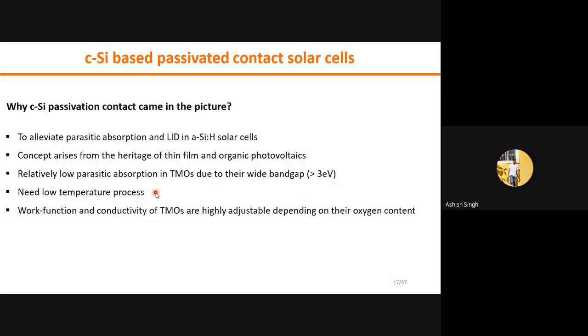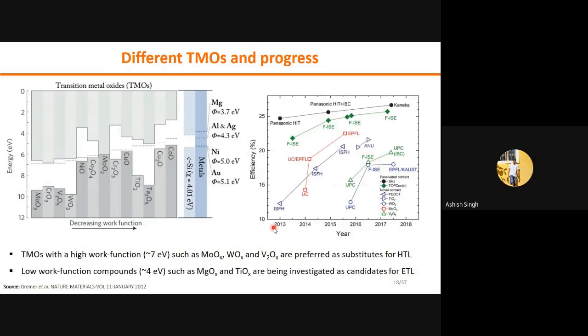And as we discussed in the previous slides, heterojunction needs low temperature deposition. This cell can also be deposited at low temperature, less than 200 degrees Celsius. And work function is very crucial to making any device. So work function can easily be tuned with the oxygen content of the transition metal oxide. So these are the different transition metal oxides used for the hole and electron transport layer.